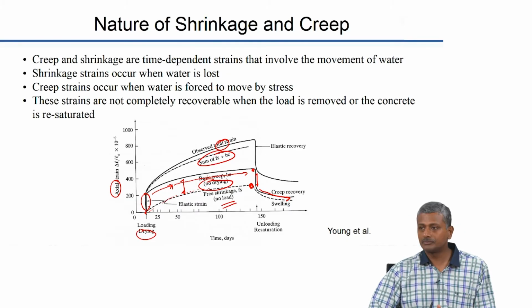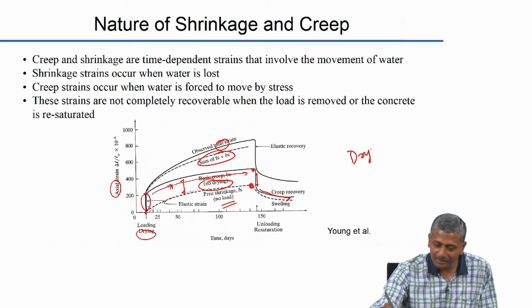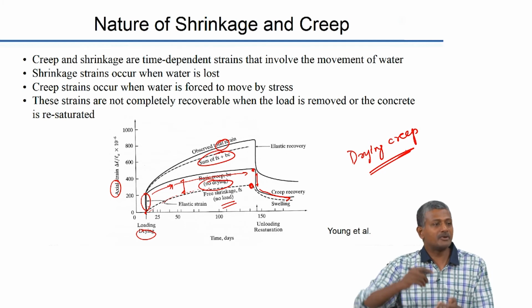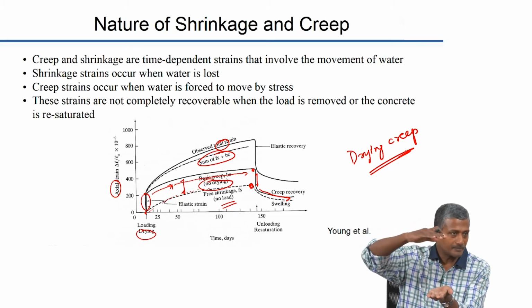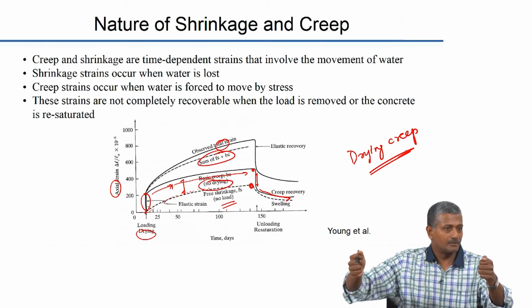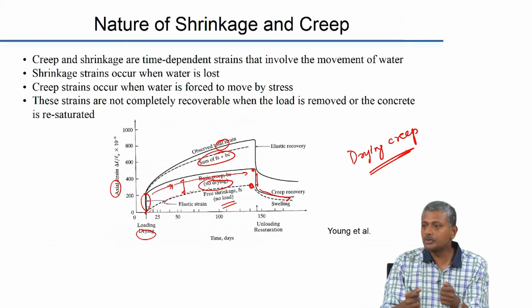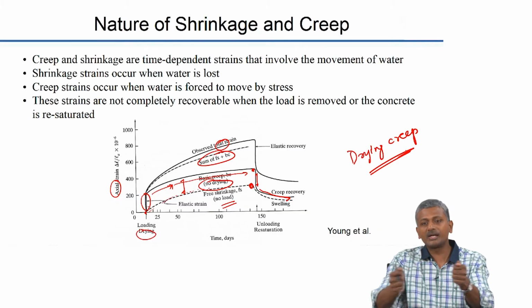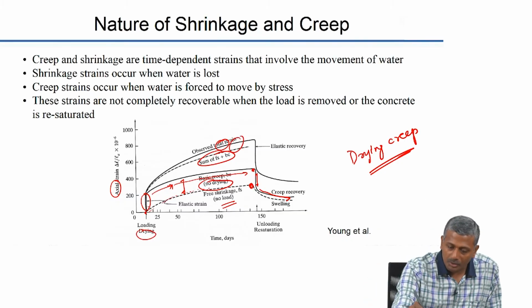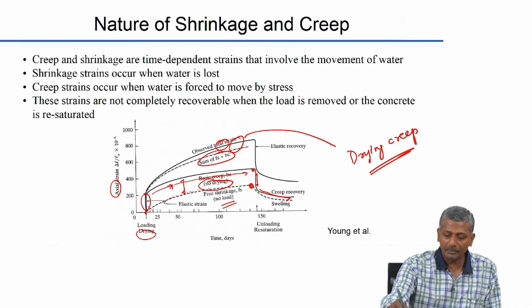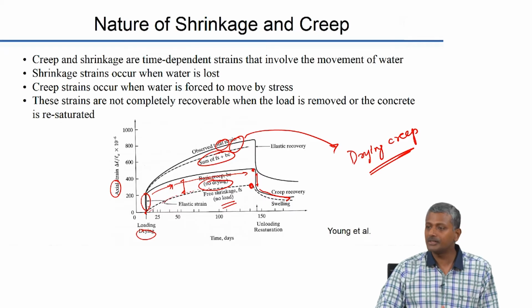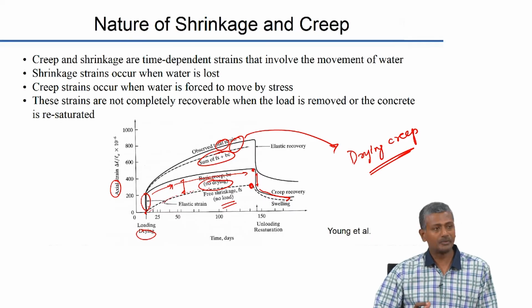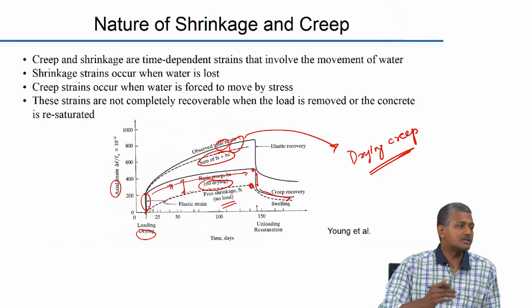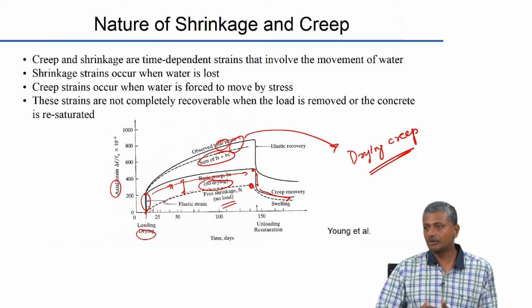What is that additional contribution? When you combine the two words, drying shrinkage plus basic creep, you get something called drying creep. Please remember, your structure is now deforming in response to the applied load and water is getting driven out of your system. So, because of drying, water is driven out of your system. Not only is the water dissipating within the material, it is also getting driven out because of drying conditions. So, this additional contribution that you see is because of drying creep. Creep that happens in drying conditions is more than creep that happens in sealed conditions. That is what you are actually observing when you see the higher strains as opposed to the total of your free shrinkage and basic creep.